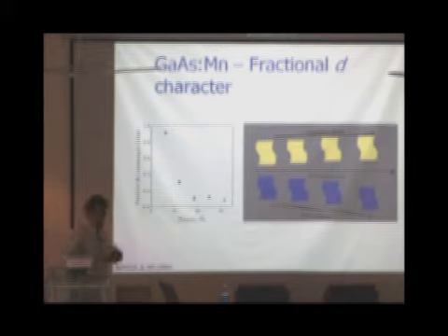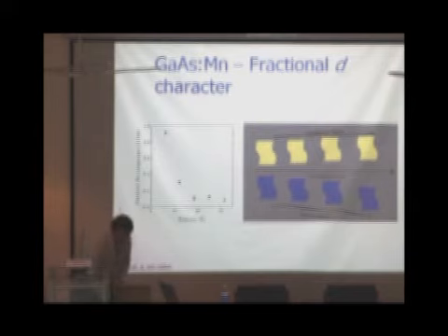The thing is that it's because of the d orbitals that are present. It's the d orbitals that are present in the highest occupied levels, so that's in the valence bands. They contribute to the half metallic character. And what happens as you keep coming down in size? Do we retain the half metallic character or not? The answer is that we do, coming from the bulk, up to about 20 angstroms, or 2 nanometers, we do retain these properties, but then it seems to drift. I'll just schematically explain that.